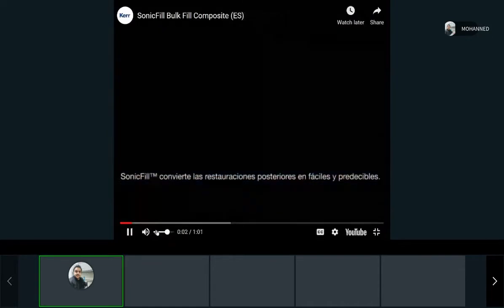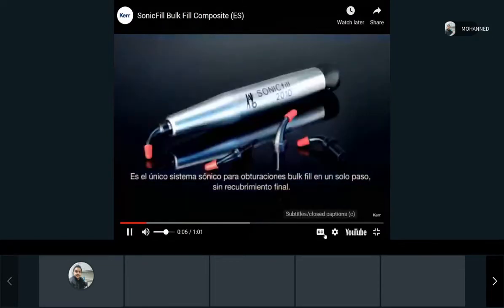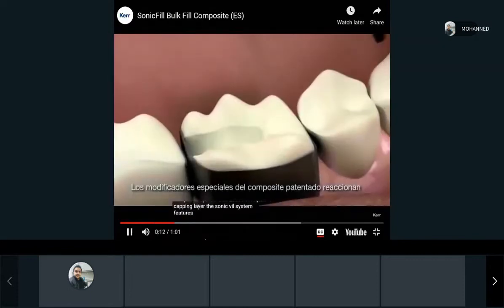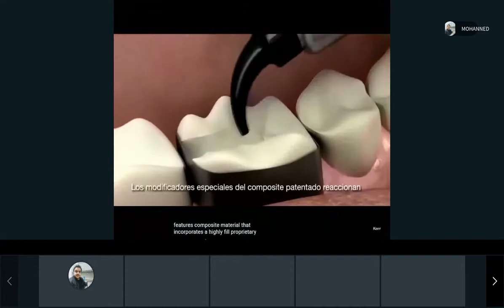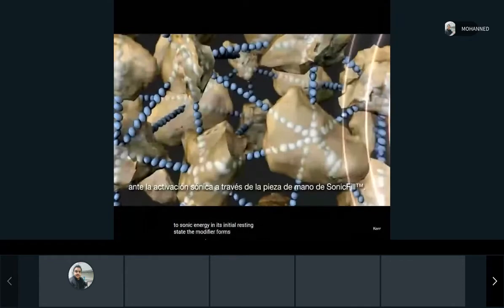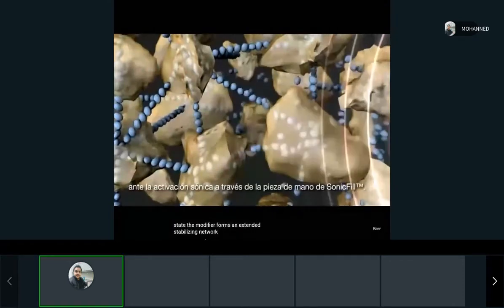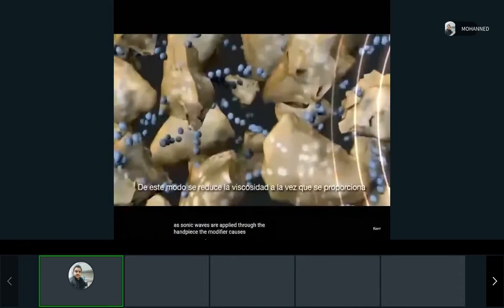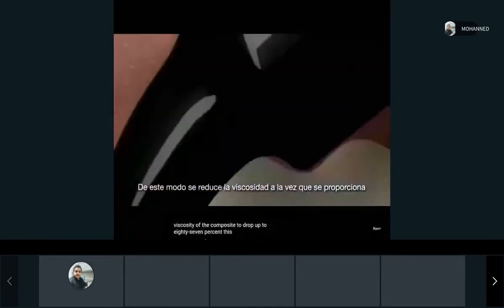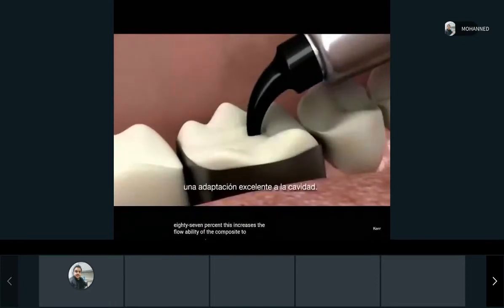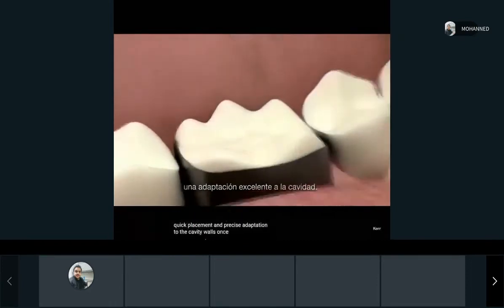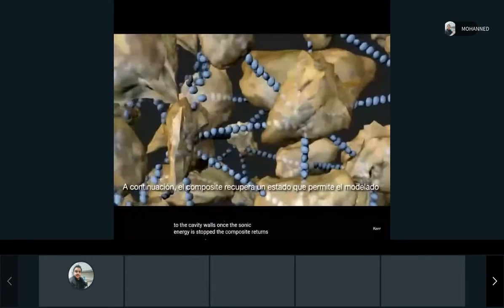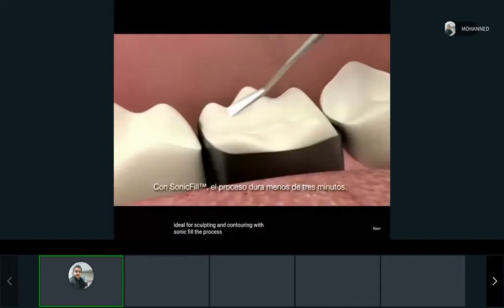Sonic fill makes posterior restorations easy and predictable. It's the only sonic-activated single-step bulk fill composite system that does not require a capping layer. The sonic fill system features composite material that incorporates a highly filled proprietary resin with special modifiers that react to sonic energy. In its initial resting state, the modifier forms an extended stabilizing network throughout the resin. As sonic waves are applied through the handpiece, the modifier causes the viscosity of the composite to drop up to 87%. This increases the flowability of the composite to enable quick placement and precise adaptation to the cavity walls. Once the sonic energy is stopped, the composite returns to a more viscous, non-slumping state, ideal for sculpting and contouring. With sonic fill, the process takes less than 3 minutes.